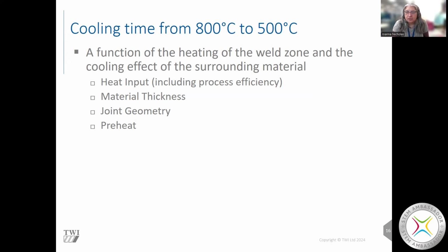The joint geometry, so if we've got a butt weld where the two plates are put next to each other and we're just joining them together, or if we've got a fillet weld, which is like a corner joint or a T-joint, then that will be a different geometry and result in a different cooling time, even if everything else is the same. And the preheat, how much heating we do of the joint before we start welding. All of those things contribute to changing the 800 to 500 cooling time.